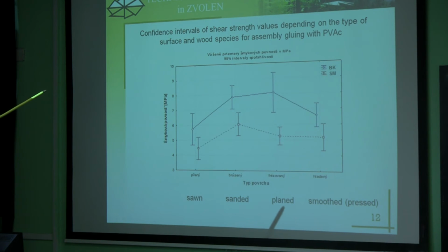had the planed surface, knife planed surface. If we have smooth or pressed surface, the openings, the fibers, capillaries or pores were closed, and polyvinyl acetate adhesive cannot penetrate into wood and cannot create any micro-dowel joints, or there is interlocking very poor. This type of gluing is for PVAC adhesive, and for PVAC adhesive, as I mentioned before, the main theory for gluing is the mechanical or interlocking theory.